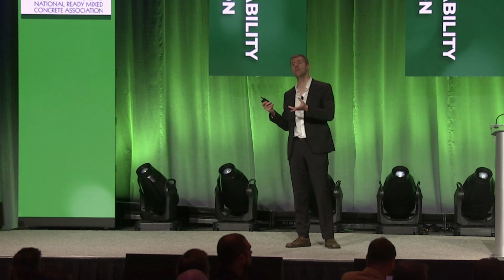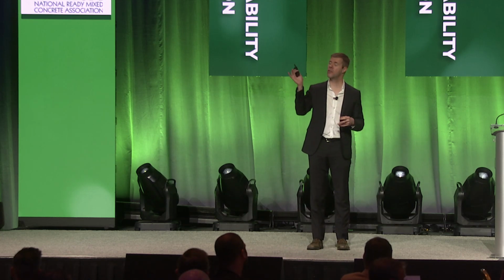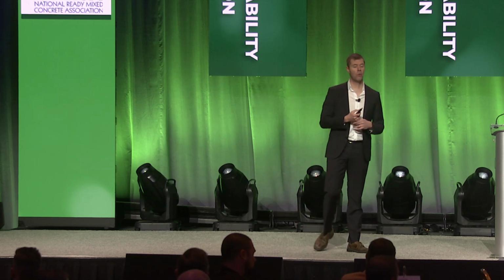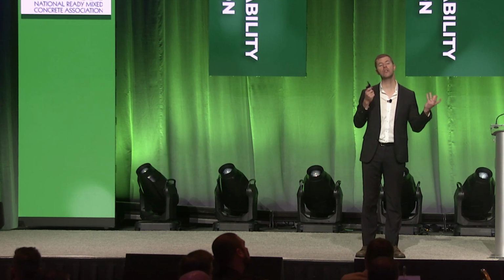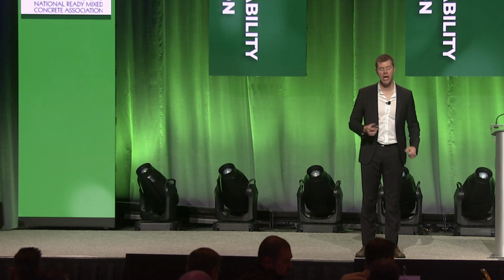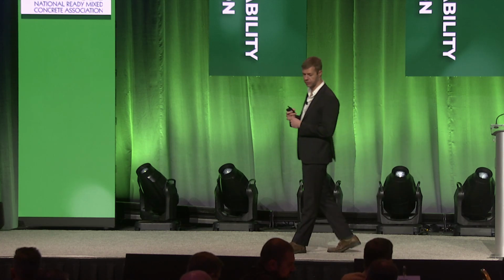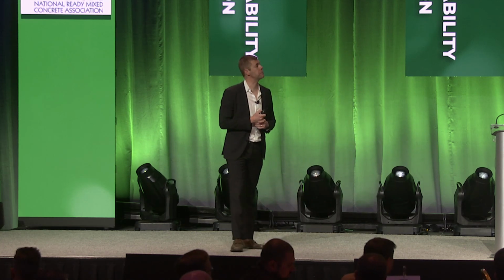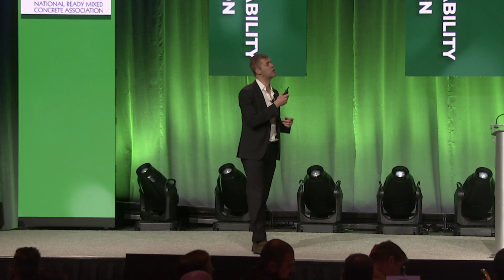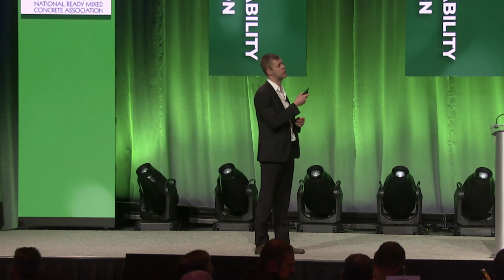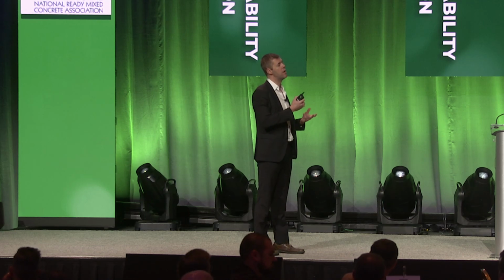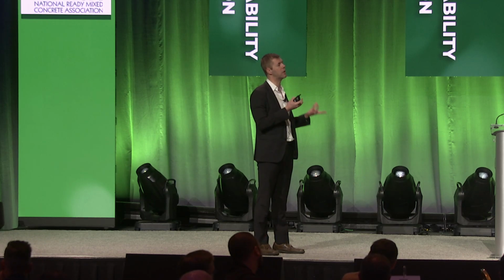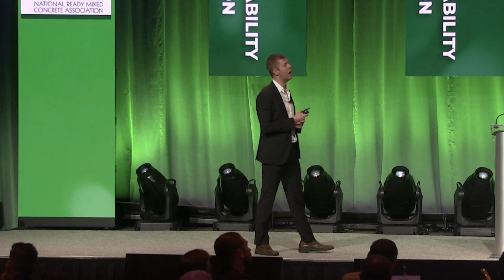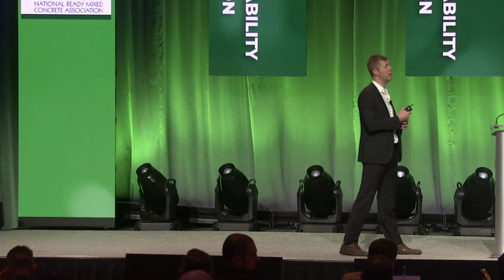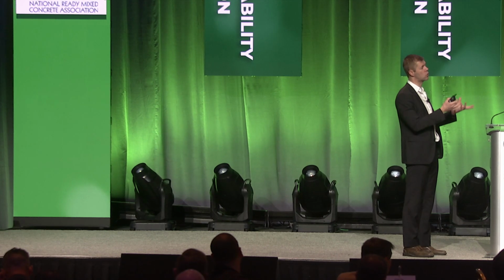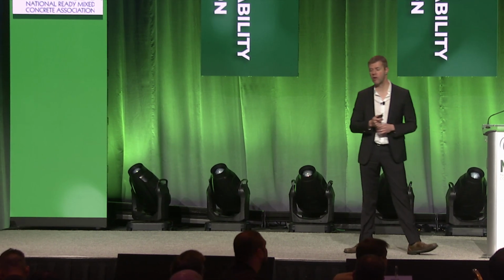Now, before I got here, I was in Minnesota. Some people in the room were in Minnesota with me. And they were talking about water cement ratio there, and they've been measuring water cement ratio for a long time in their ways, and they've been looking at the Phoenix for about 3 summers now. Where they had been just measuring mixed water and aggregate moistures to get a water cement ratio, they've now been using the Phoenix, and typically they were about 0.02 to 0.03 higher than what they were getting. That means just some water's finding its way into the mix, but everything is great. They're happy, they're excited, they were very pumped about that.